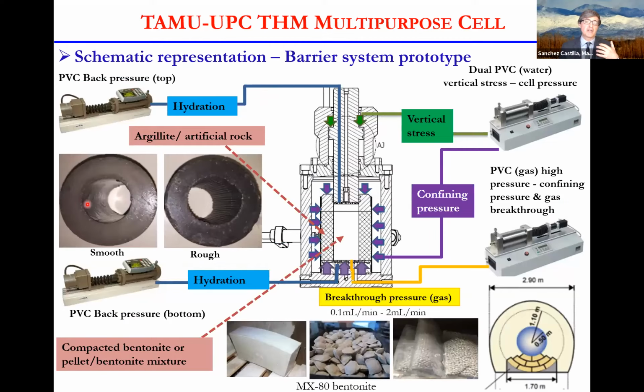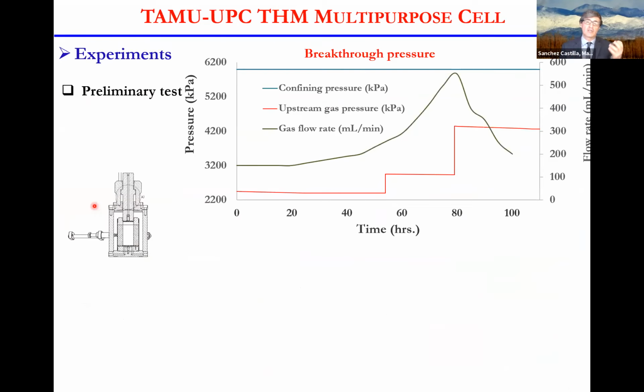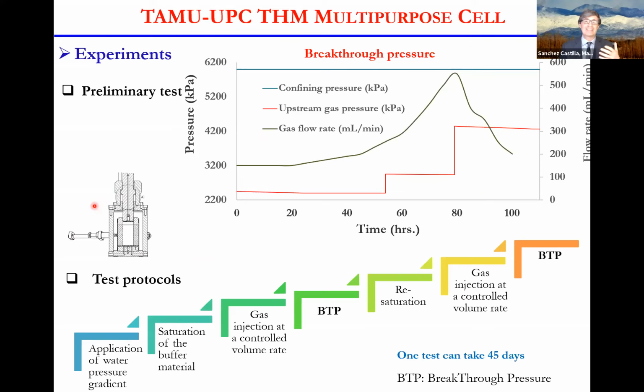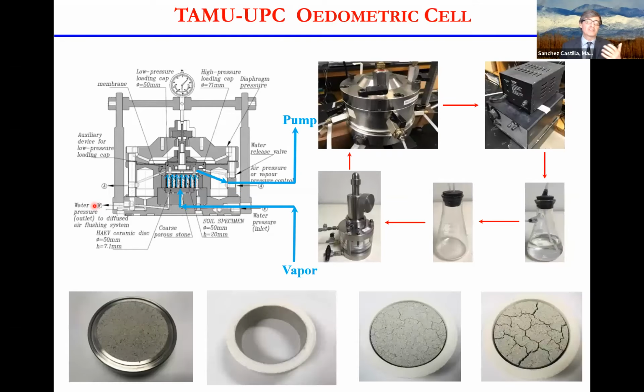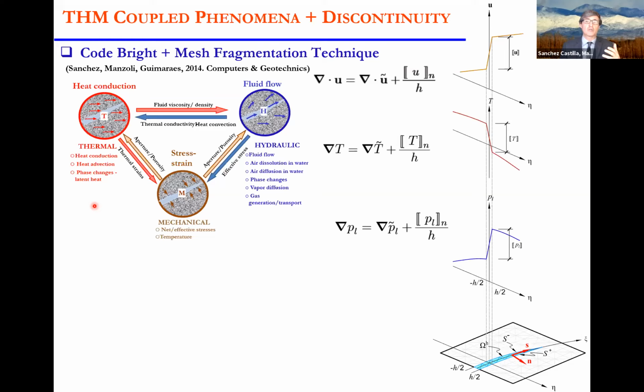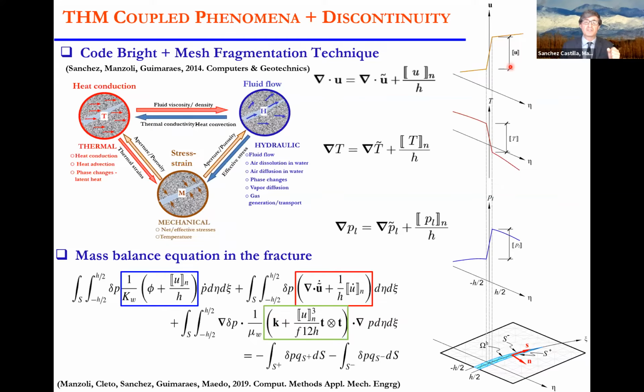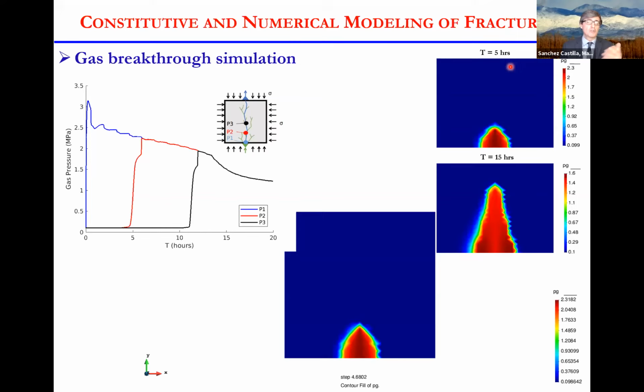We are looking at different kinds of interfaces to see how the roughness of the rock wall will impact this gas migration. And we are following different protocols to understand better how gas will migrate in this kind of system. We also anticipate that this bentonite might dry and might open cracks. So we are looking also at whether this is a possible scenario, and in this case, how gas will migrate through this cracked soil. We also developed and upgraded our code to account now for this jump in the displacement, temperature, and hydraulic fields, so we can account for the presence of discontinuities in our system. And we are using this code to model this problem of gas breakthrough, opening of the fracture, and gas flow.